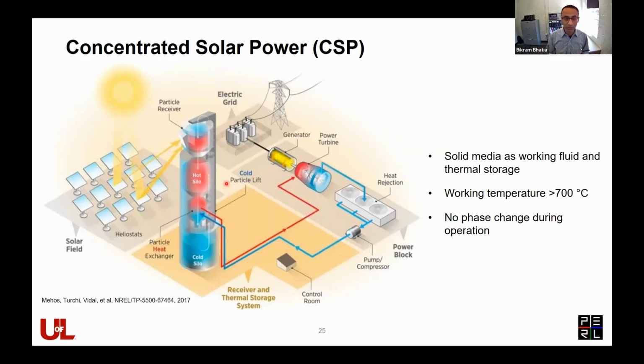And there's no volume expansion associated with it. So it's pretty easy to store. And you can go to relatively high temperatures, on the order of about 1,000 degrees or so. And so when you have to deliver power, you basically pass this hot sand through a heat exchanger, and you have a secondary fluid, typically supercritical CO2, which drives a power turbine based on the Brayton cycle, ideally at high temperatures to produce power.